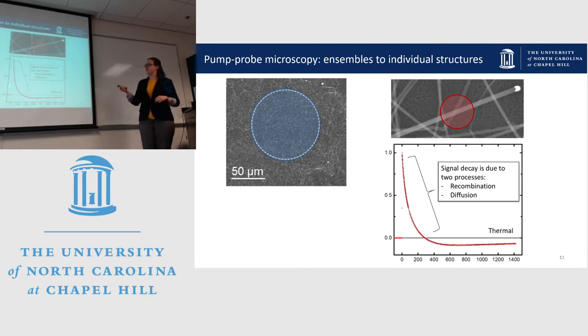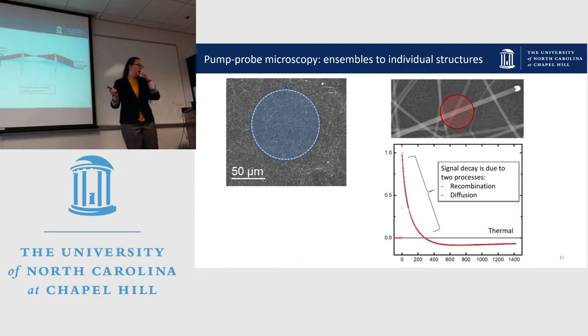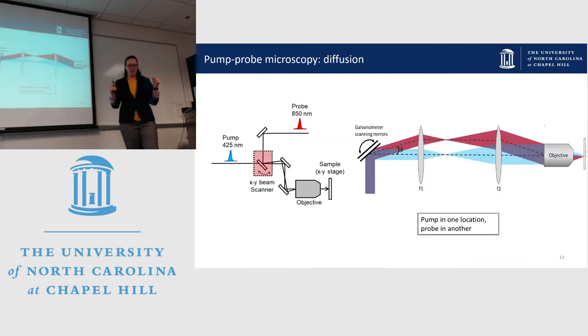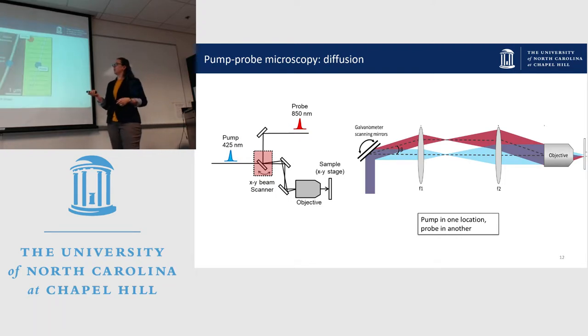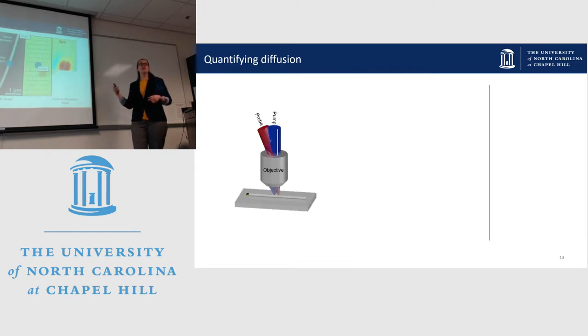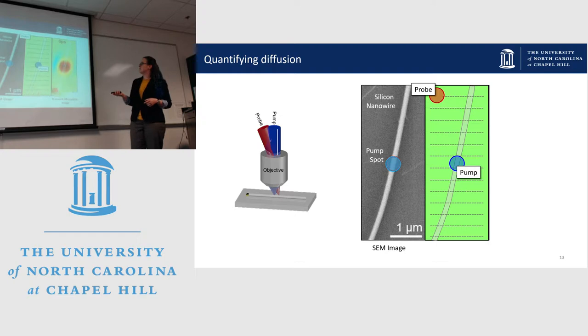So in order to fit this and get an accurate lifetime, we need to know how quickly the carriers are diffusing. And so we do this using something called spatially separated pump probe microscopy, where we pump our carriers in one location and we probe in another. And we do this by changing the angle that the beam goes into the objective. If you change the angle of entry of the beam, you change where on the sample it focuses. So, like Erica showed, we can pump in one location, raster scan the probe across the sample, and generate a map of where carriers are at a given point in time.